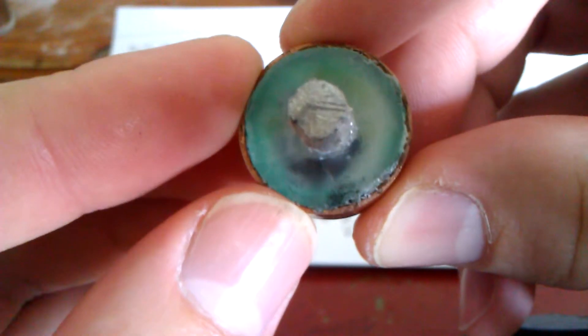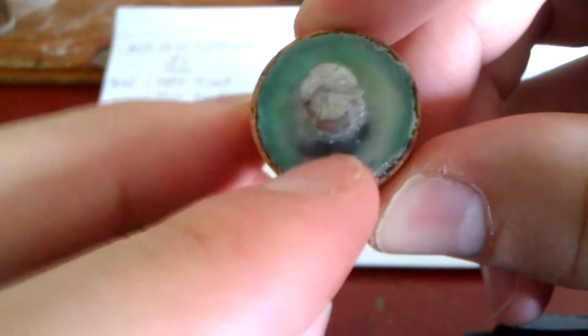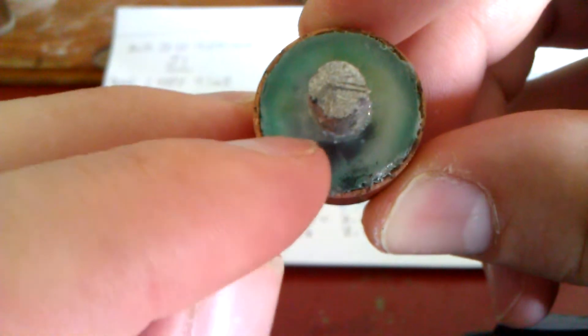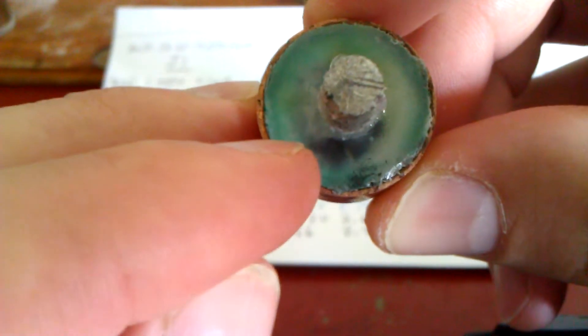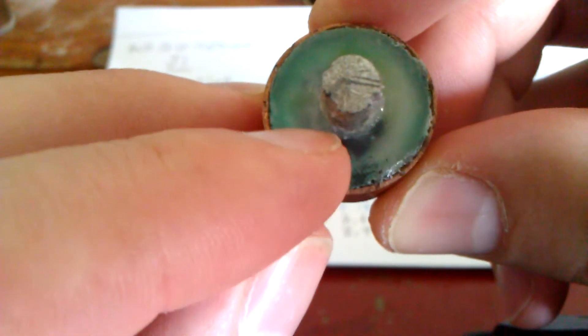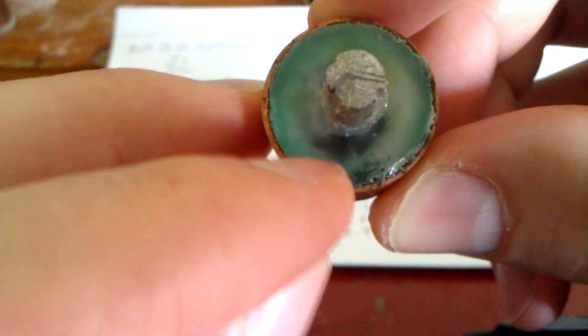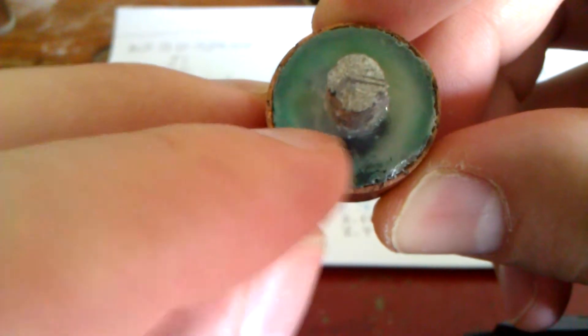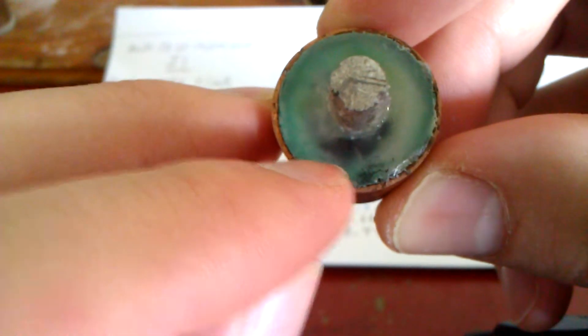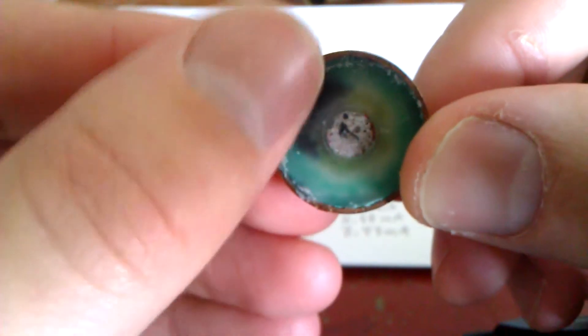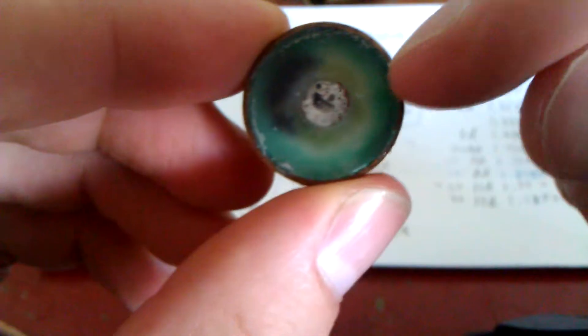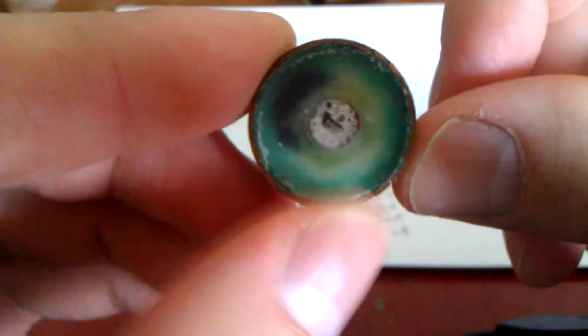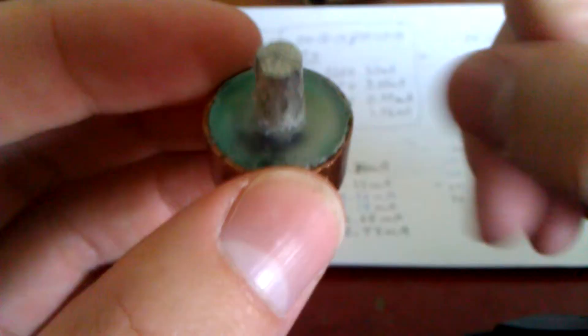So you can see there's one very dark black area, and it's not touching the magnesium, it's hovering around it. So that's why I believe that the dielectric grease is causing some kind of oxygen-starved reaction, and that's what that's from. And it's on the other side, it's even worse, but it's only in one spot. You can see it's also losing most of its color, except for around the magnesium, which is very interesting.